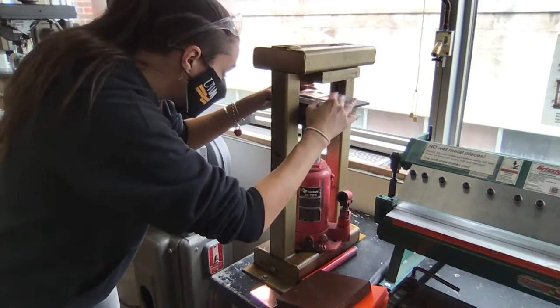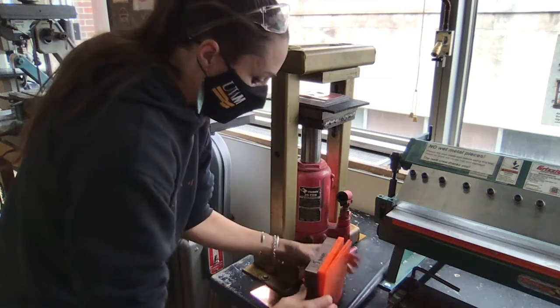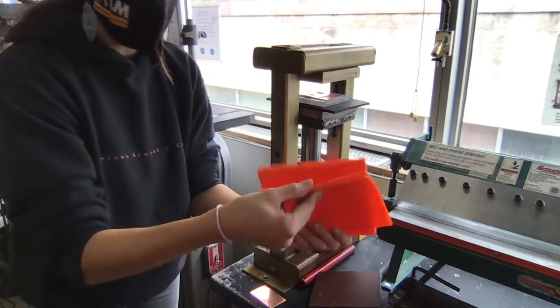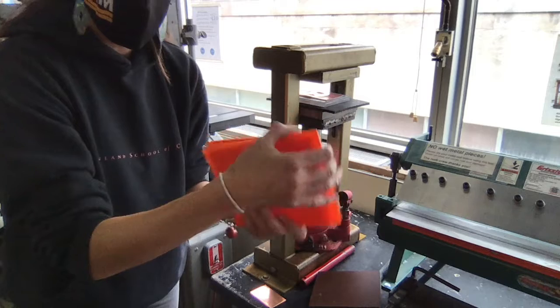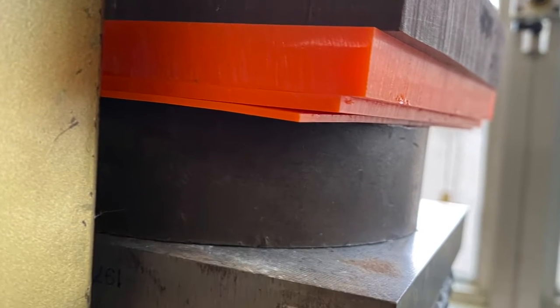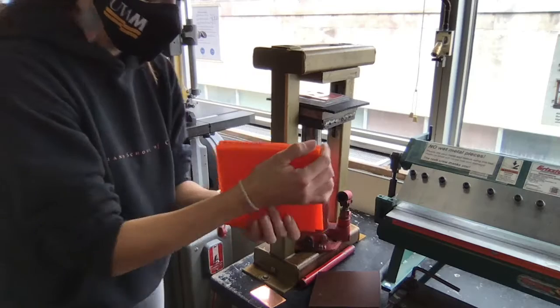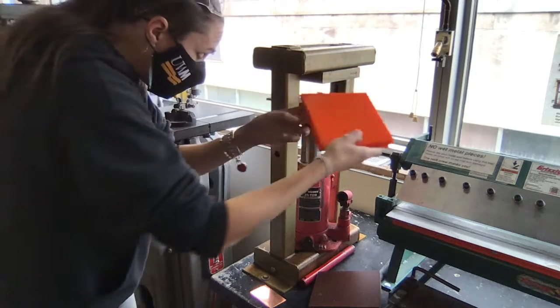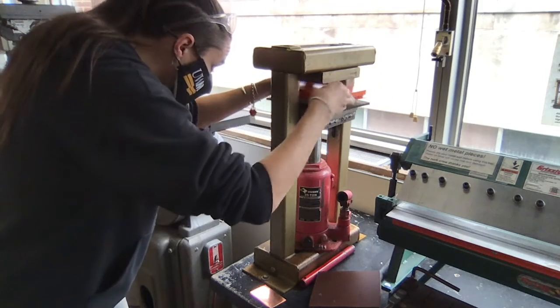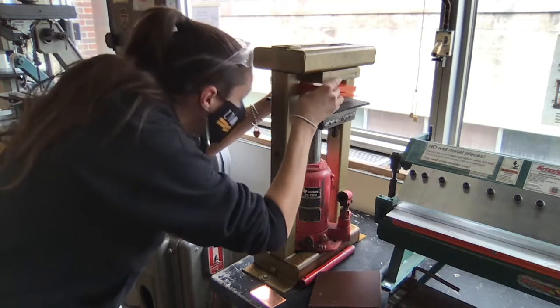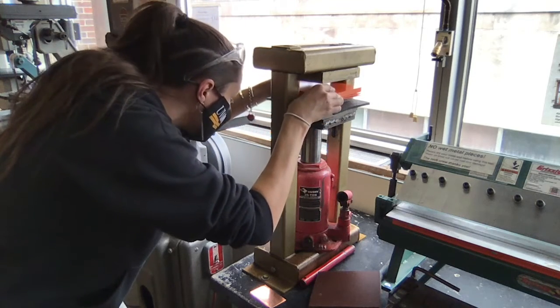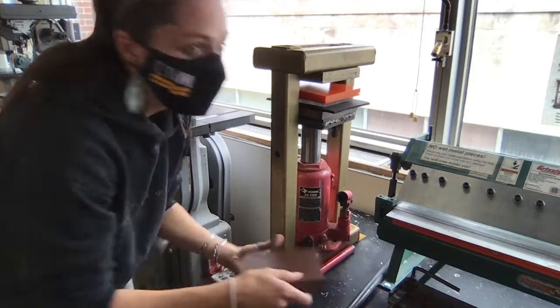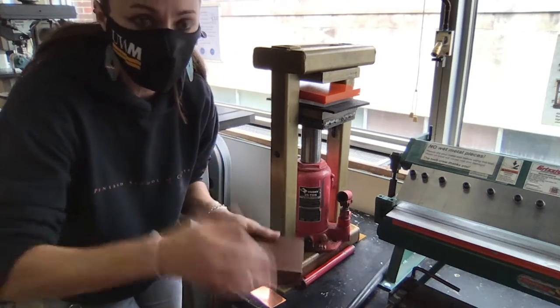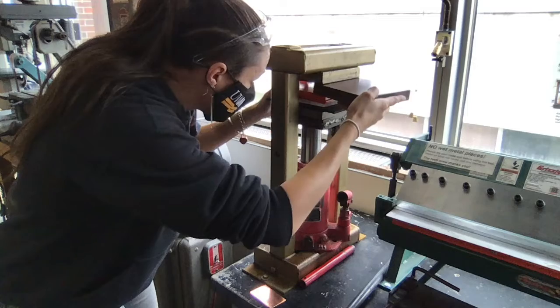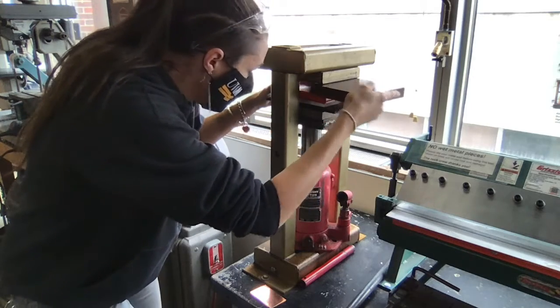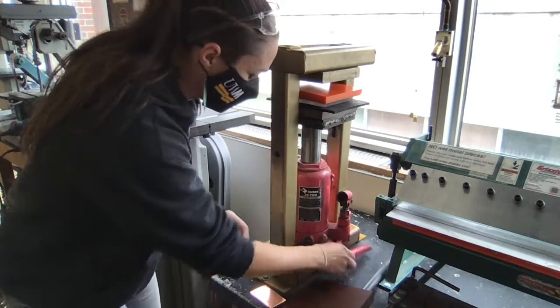So I want to make sure that's directly centered in the middle. And then I'm going to add my 3 layers of 80 durometers, starting with the thinnest layer on the metal. Stack all 3 of these on top and centered. Make sure not to move the metal when you're doing this, and make sure it's centered. This is the only time that you have to worry about the metal shifting around when it's in contact with the die. After this, if you just want to go deeper or you have to re-anneal, the metal will be locked into position.